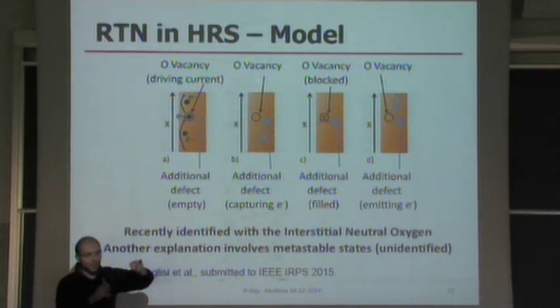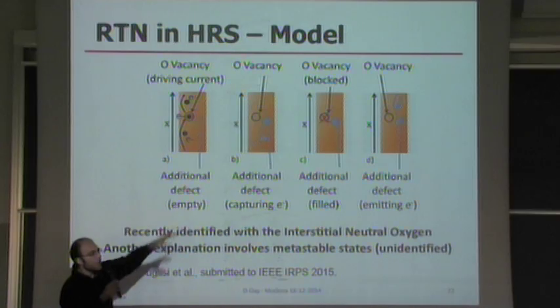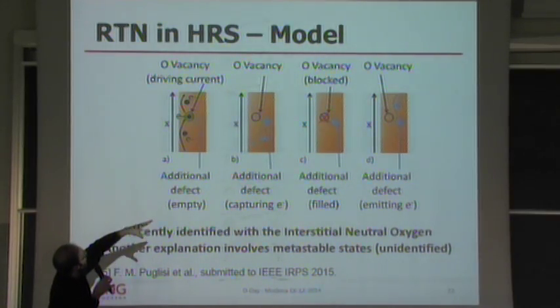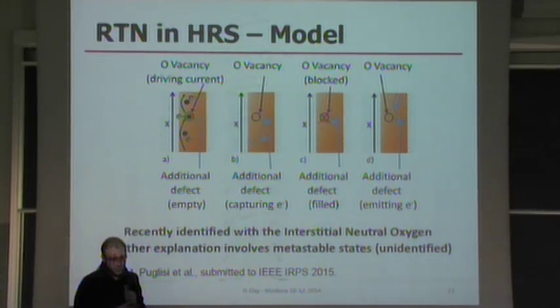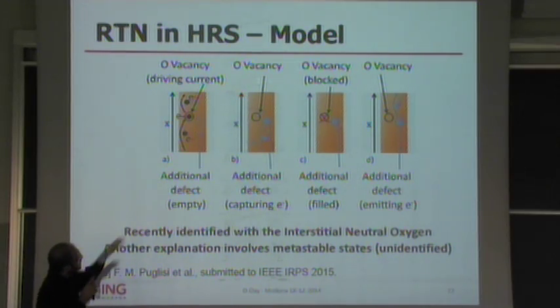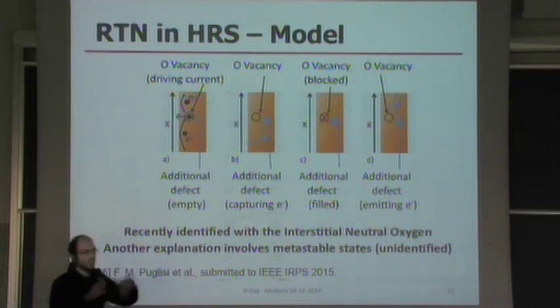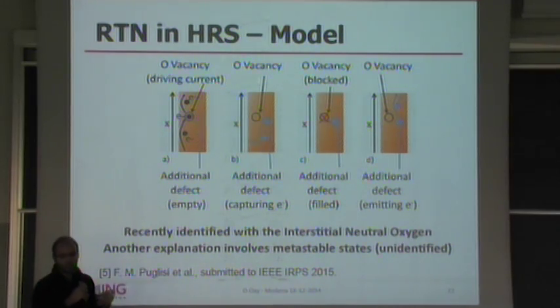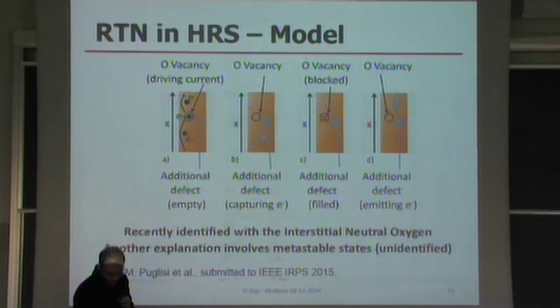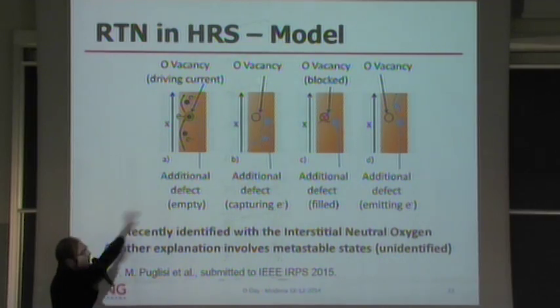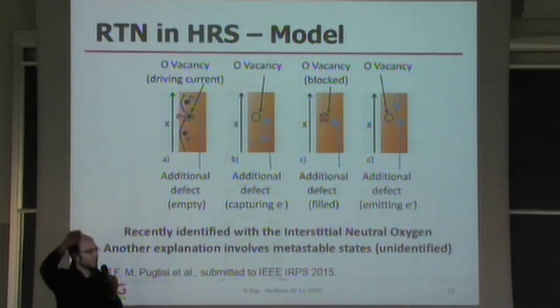So when we capture and emit charge from this additional defect, we can disturb the properties of a close oxygen vacancy. And actually we recently identified this additional defect with a species naturally present in the device, which is the interstitial neutral oxygen, and we are sending this paper to IRPS, so keep your fingers crossed. And another explanation exists. It involves metastable states, so no additional defect. The oxygen vacancy for some reason can go into some metastable states during which it cannot assist the current. They are still unidentified in this structure.